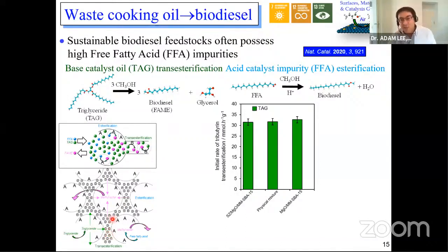So how does the catalyst actually perform? Well, if you look over here at the graph, what you find is that if you feed any of these catalysts pure triglyceride, a pure oil, they all do very well. So a pure base catalyst is okay for making biodiesel as long as you have a pure feedstock. So our spatially orthogonal catalyst performs just as well as a physical mixture of an acid-base catalyst or a pure base catalyst. However, what happens if we take our pure oil and we throw in a lot of acid impurities that occur in real used waste cooking oils?